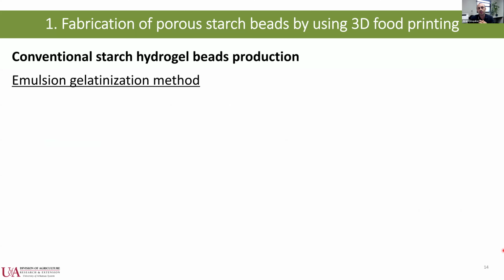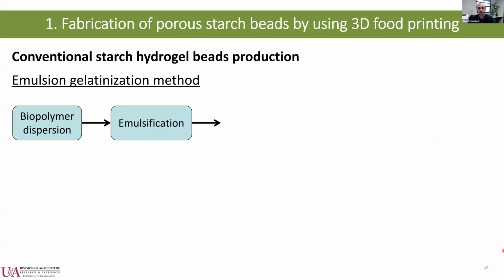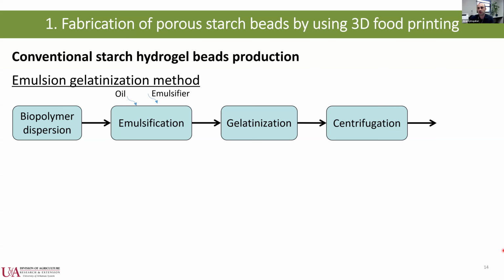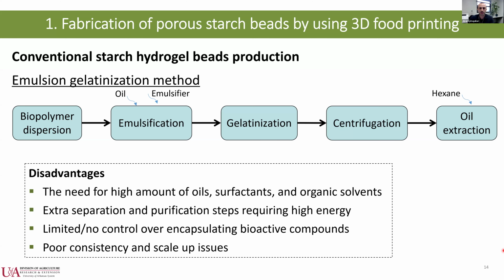So before we start on how we are using 3D printing to create those particles, first let's look at the conventional way that we have been using to create hydrogel beads, especially from starch. The common method is called the emulsion gelatinization method. What you do basically here is create a polymer dispersion. So you create starch in water, and then you emulsify that. You use oil and emulsifiers, and eventually we heat the system up so that the starch dispersion gets gelled, where you have kind of droplet hydrogels, and then you do centrifugation to separate the particles. And eventually you need to extract the oil back using generally a petroleum-based solvent, which is hexane.